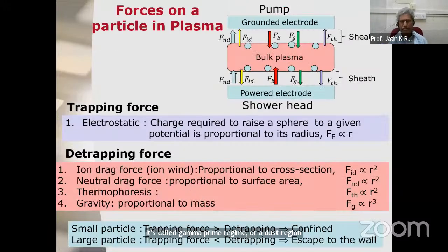So how are the particles collected then? This is how you can see them. This is the plasma bulk. Let's say the particles are formed here. There are two things happening. The particles are negatively charged, so they're trapped inside by the electrostatic force, which depends on the radius of the particle and is allowing the particles to stay inside. That is called the trapping force.